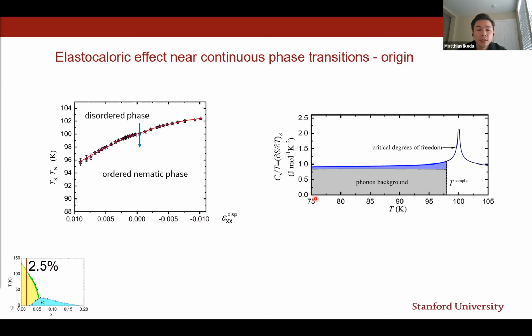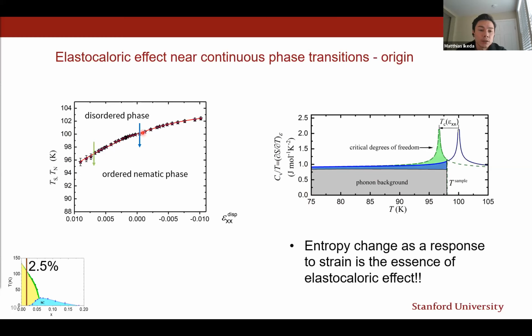Now, in this particular instance, I have chosen the sample temperature to be slightly below the phase transition temperature. And so we can now calculate the entropy by just integrating this quantity from 0 up to the sample temperature. And the entropy is going to be corresponding to the colored area here. In this example, if I would now apply tensile strain, then the phase transition would shift to lower temperatures. And therefore, the feature associated with the phase transition in the heat capacity, of course, will also move to lower temperatures, increasing the entropy of the system by the area that's shown in green here.